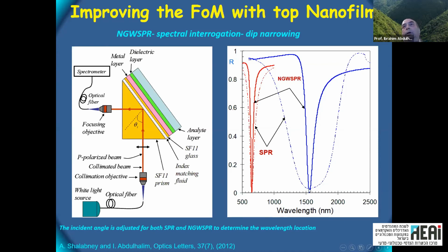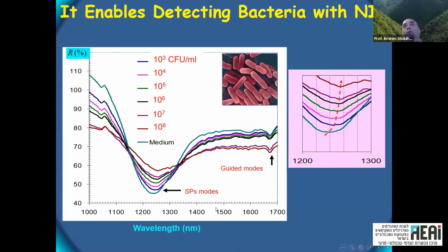Because it's in the NIR, you improve the penetration depth, so you actually can detect bacteria. And this shows that the signal is monotonic with the bacteria concentration. As you can see here, the shift is monotonic. When you do that with the standard SPR without the 10 nanometer silicon, then you don't get a monotonic signal.